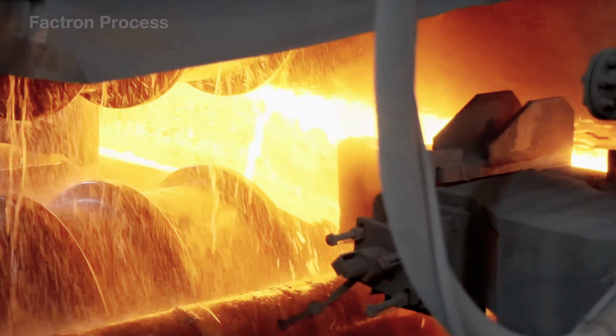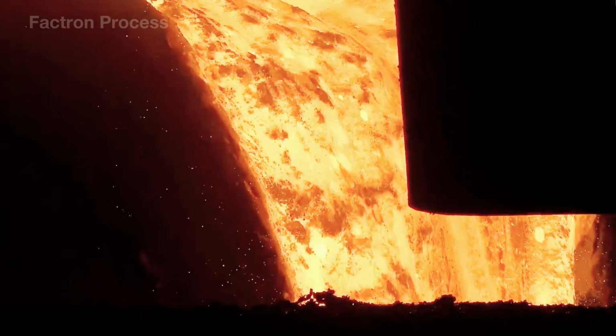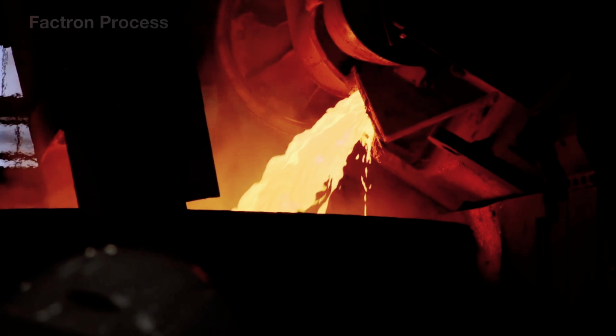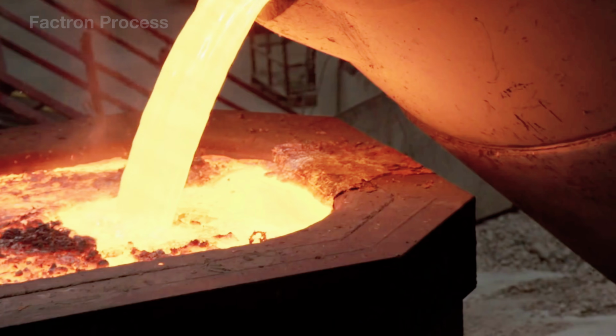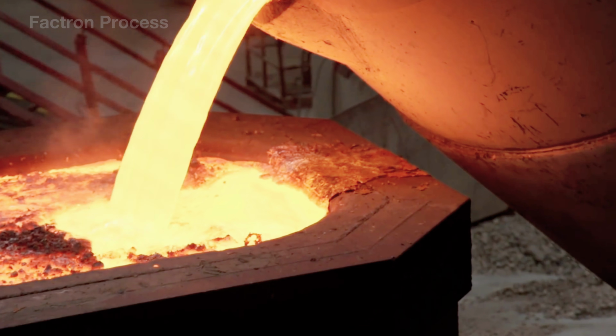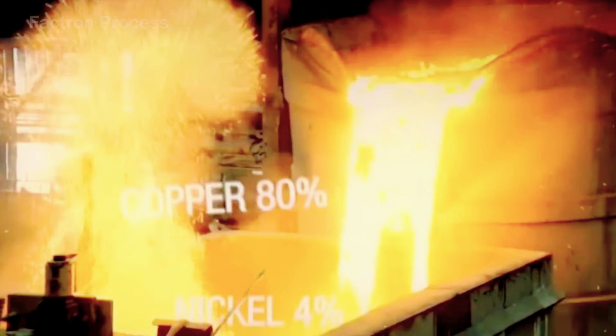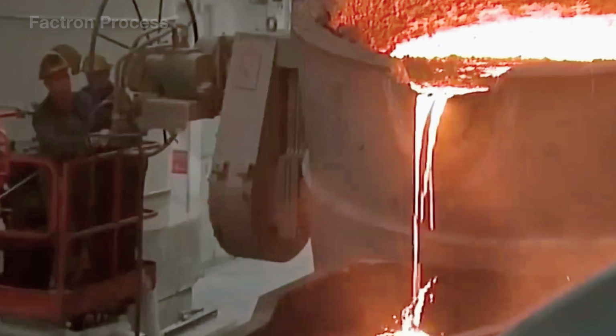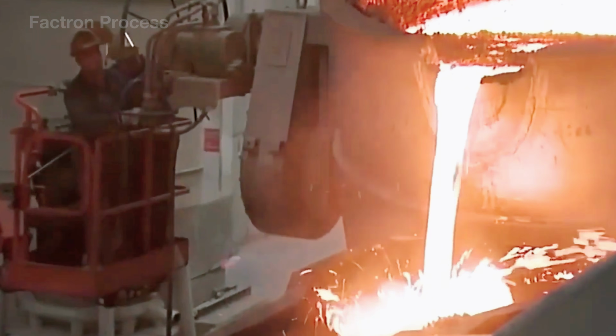Sensors continuously monitor the temperature while workers remove the slag floating on the surface. Only when the temperature, cleanliness, and alloy composition meet the requirements is the pouring ladle lifted from the furnace and slowly transported toward the mold by an overhead crane. For a large propeller, this process may require 40 to 80 tons of molten metal.